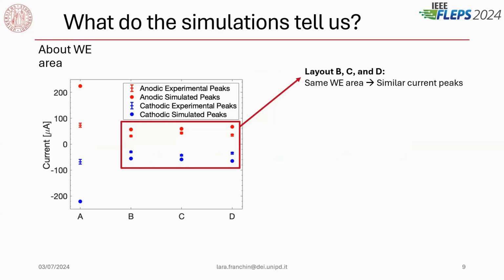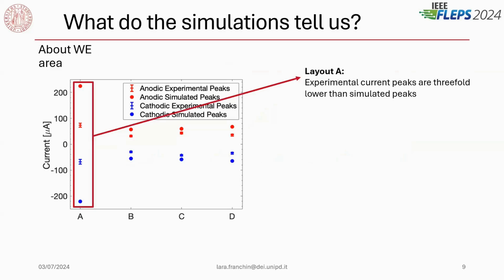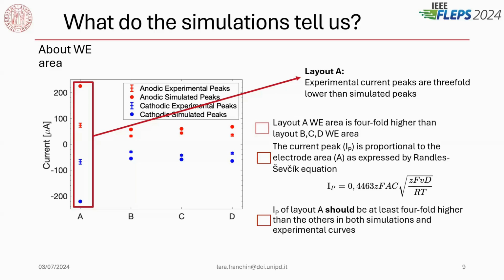About the different areas, if we take a look at layouts B, C, and D, they have indeed similar current peaks, which is actually fine because they have the same working area. But when we take a look at layout A, we can see that the experimental current peaks are much lower than the simulated one. And why so? Because we are, of course, expecting at least a 4-fold higher current peak for layout A.